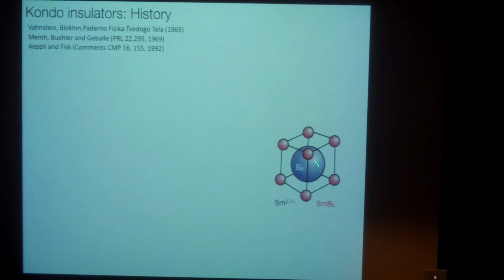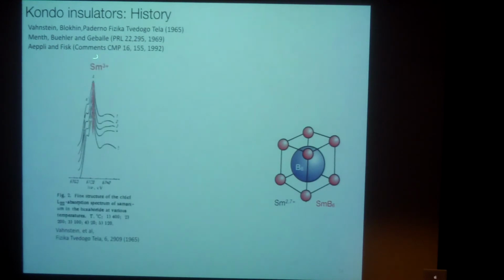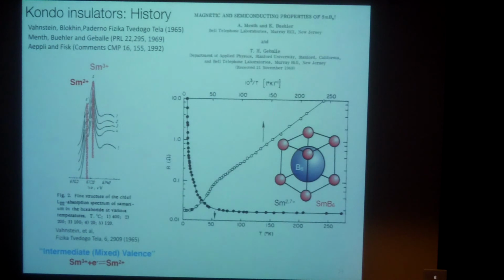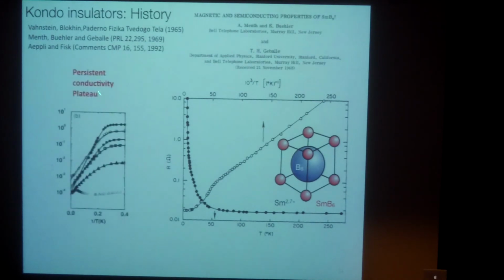And it used to be thought that samarium hexaboride was a conventional insulator. It's been studied for almost 50 years. Here's some old data from 1965. Here is the resistivity measured by Ted Geballe's group at Murray Hill in those days, showing the growth of resistivity, the formation of a gap in a sort of metal at low temperatures. And here is the persistent resistivity plateau that's been seen for more than 30 years, and no one knew that it was topological.